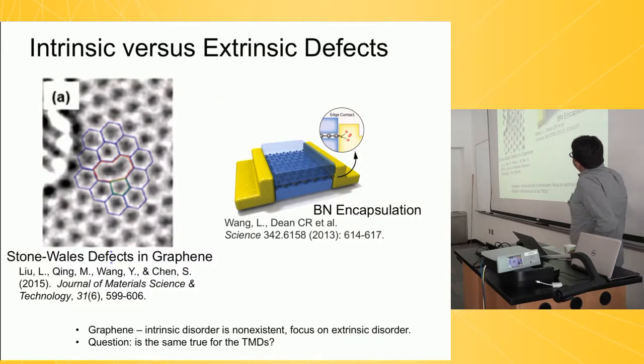Okay, so the next important thing that I want to talk about is to distinguish. I'm going to talk about defects. And so we should ask, for a two-dimensional material, there are in general two types of defects that influence the properties of a two-dimensional material. One is, if I take a two-dimensional material, this is graphene, you can create a defect inside the crystal lattice. So this is one of these defects. In this particular defect, the 6-membered carbon rings are broken into 5-membered and 7-membered carbon rings. This is called the Stone-Wales defect.